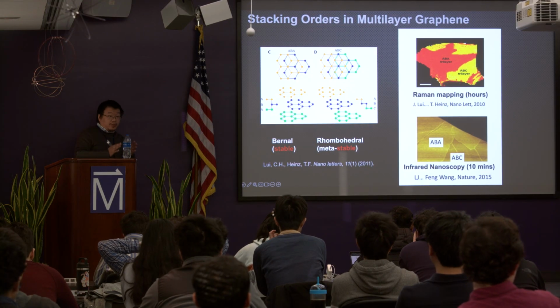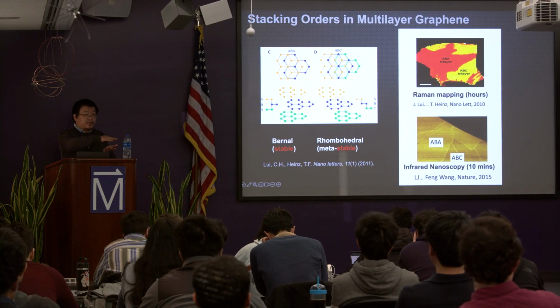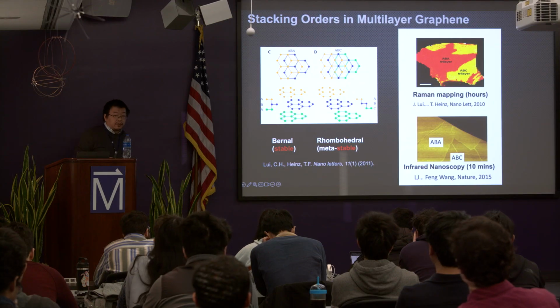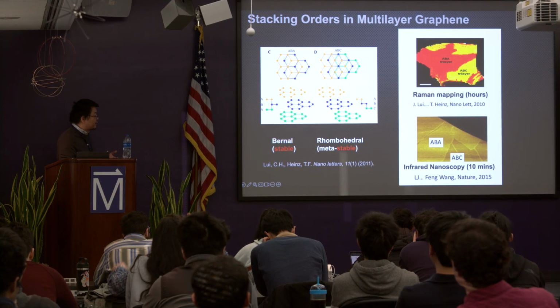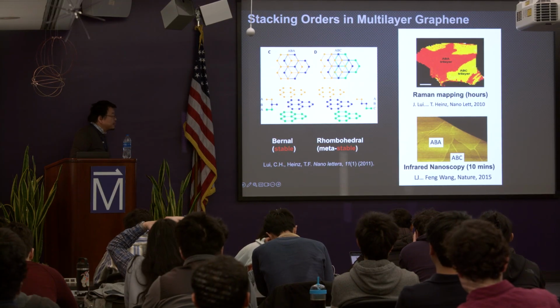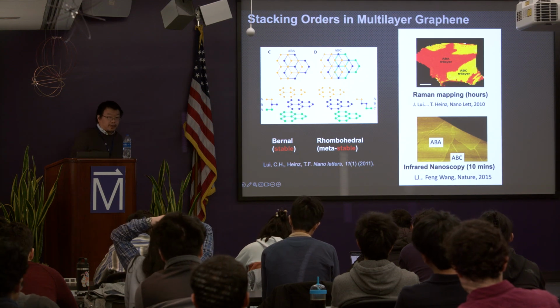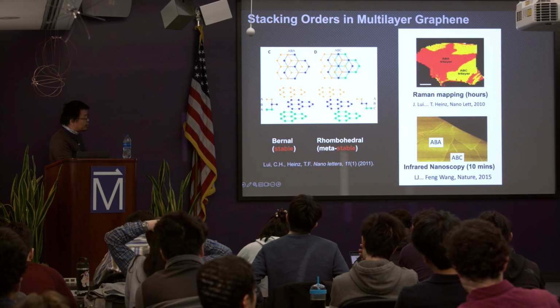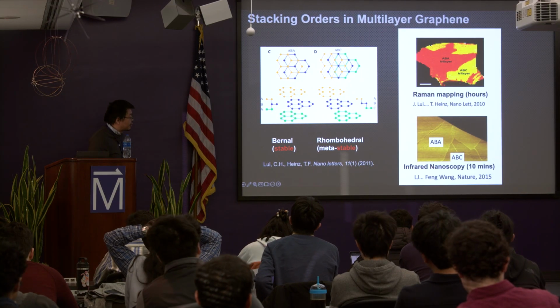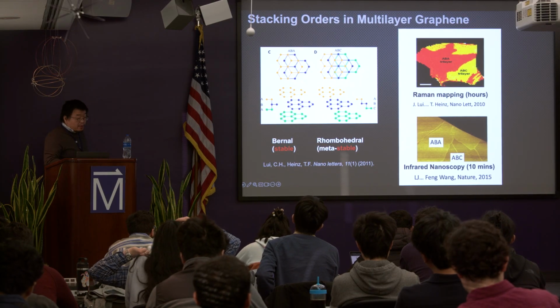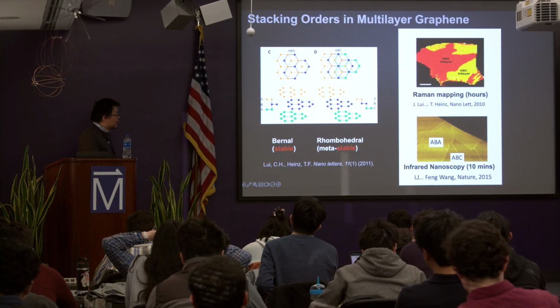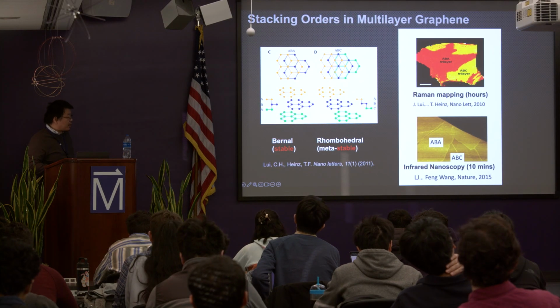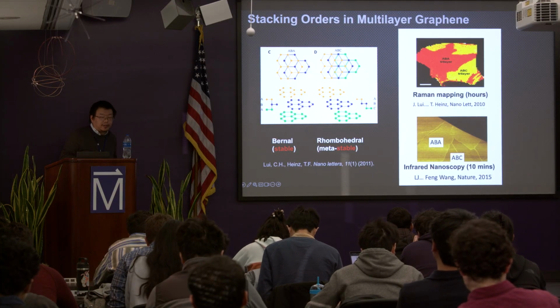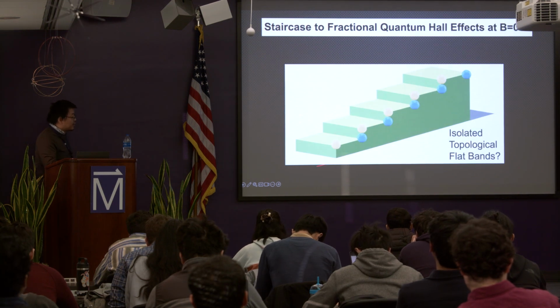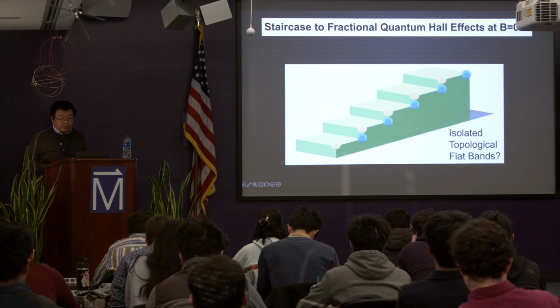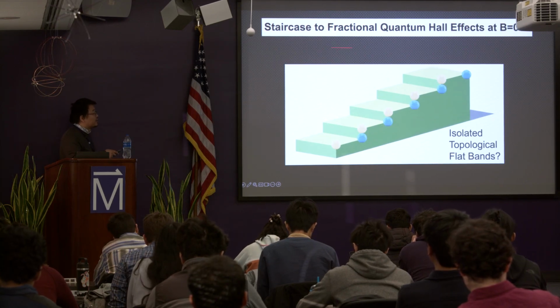But do be aware, when I say stacking, I don't mean that you have each different single layer and you manually stack them together. Rather, you just exfoliate from the bulk graphite, so this naturally exists. Then you can use an optical method to separate these two stacking orders because of the optical conductivity difference. You can see in this case, you have a pretty big difference between the ABA stacking and the so-called ABC stacking. So this staircase form of graphite is what we're interested in. It's actually metastable, but it still naturally exists, about 20% in natural graphite. So let's see if we can get really isolated topological flat bands, which may lead to the fractional quantum anomalous Hall effect.